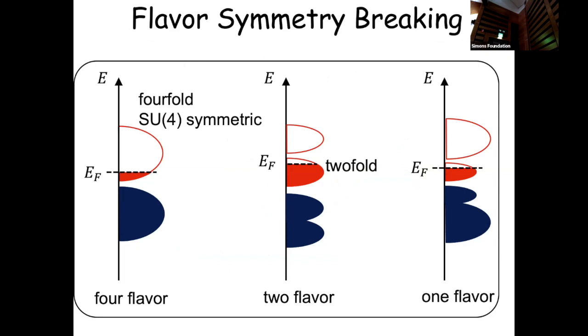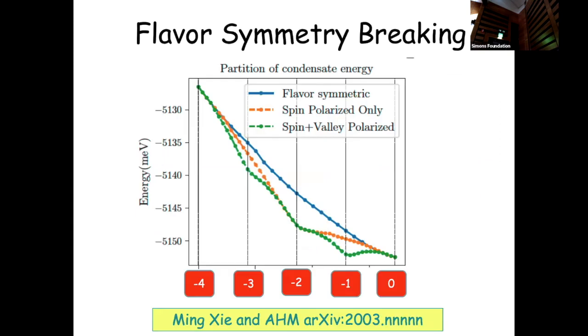I have to skip the quantum anomalous Hall effect. But the important point is that these broken flavor symmetries, spin valley flavors, it seems quite clear that they occur through most of the metallic regime, most of the non-integer filling factor regime, which of course we can explore with doping. Mean field theory calculation says we should expect that the broken flavor symmetries that occur in insulating cases should occur also over much of the